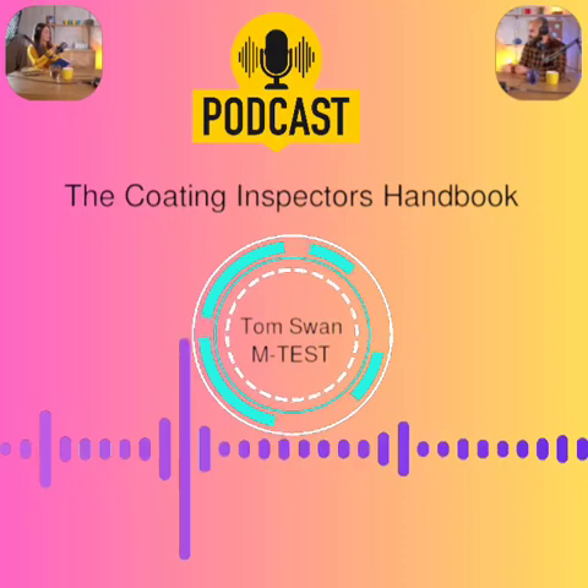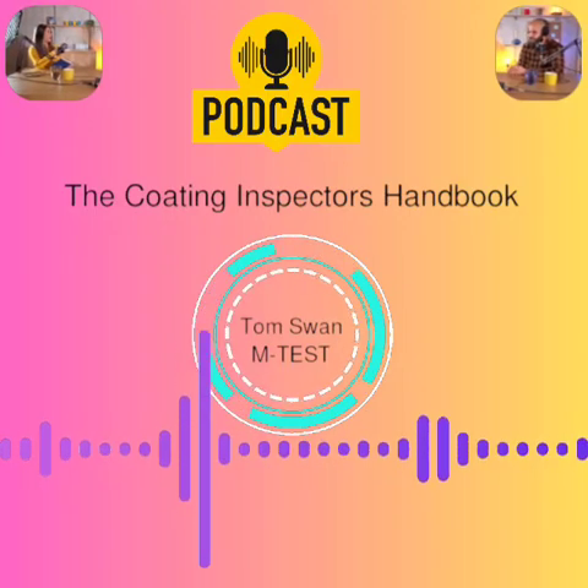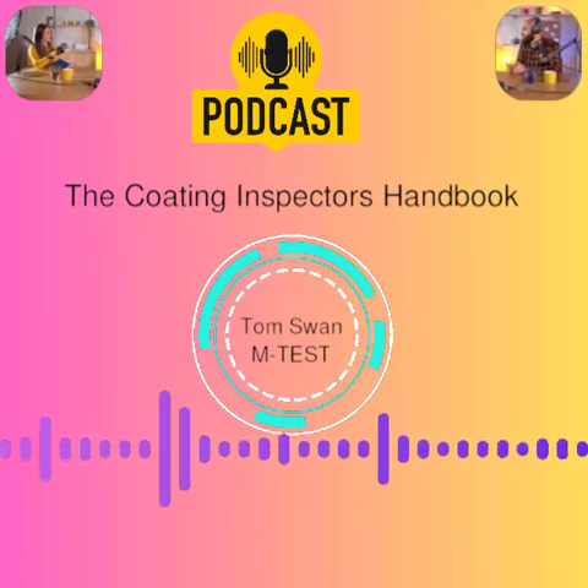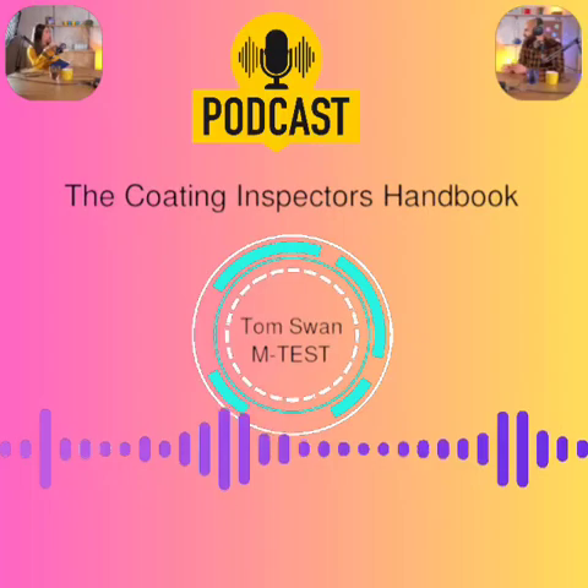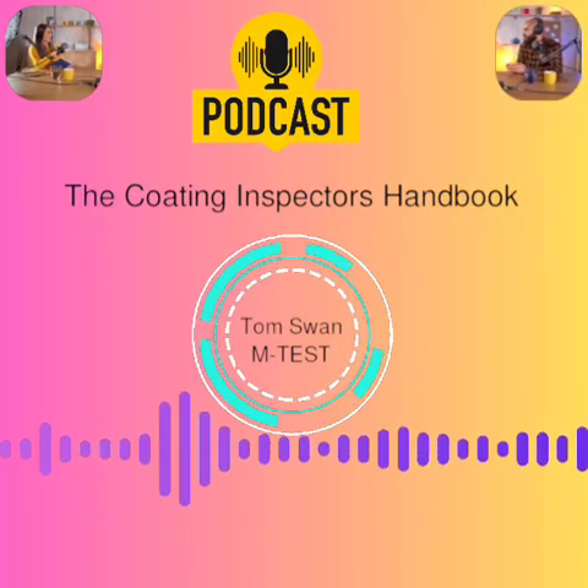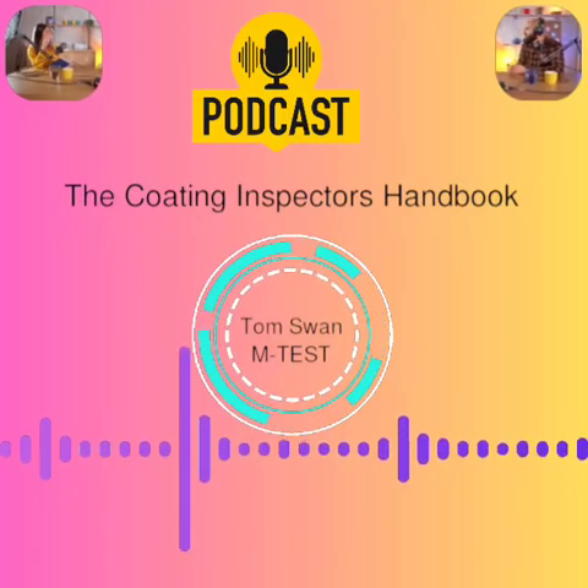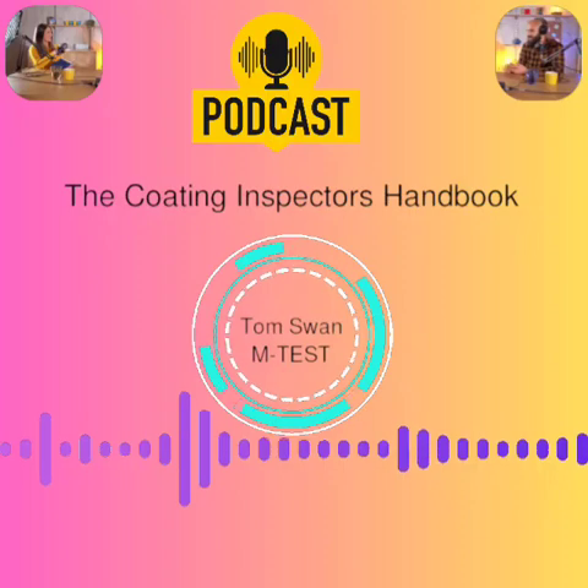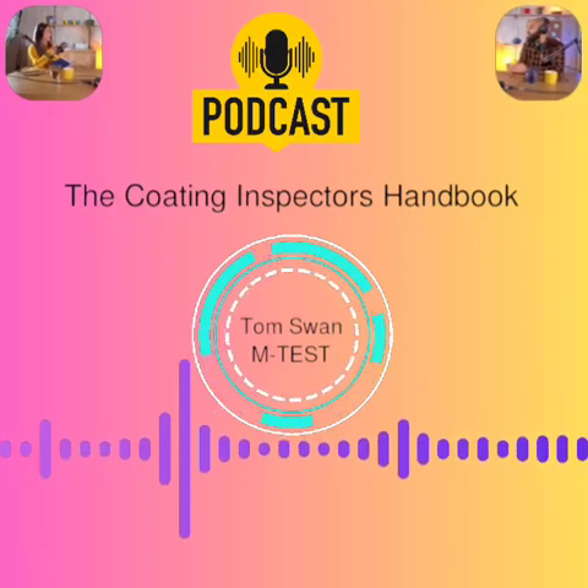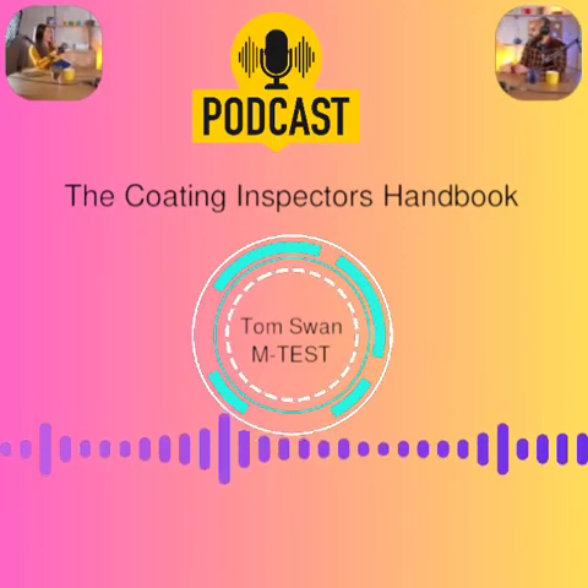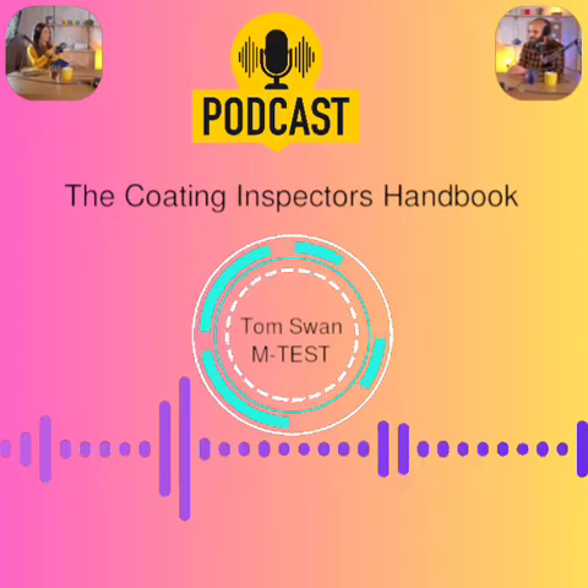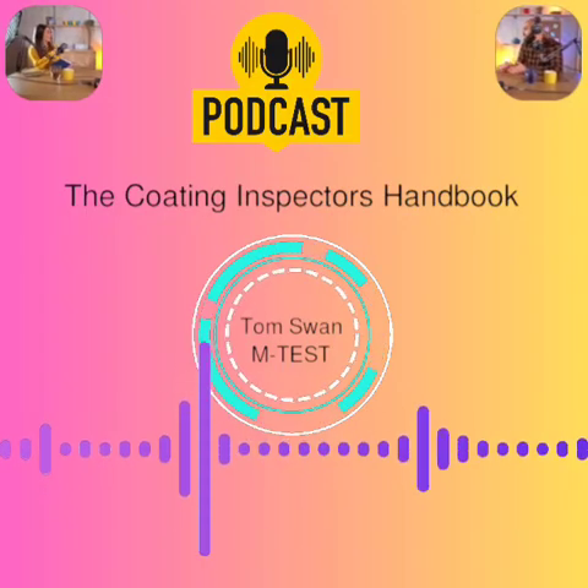How accurate is it? Not very precise numerically. Lots of variables affect it. Blade sharpness, dirt, coating elasticity, substrate, scoring technique, pull angle, pull speed, tape quality. So the rating is simple? Yeah, 0 to 5 scale based on % area removed. Avoids false precision. 5 is best, less than 5% removed. 0 is worst, over 65% or total removal.